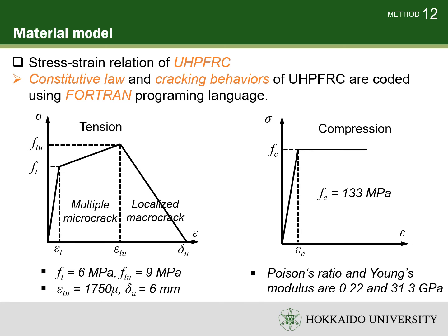Material model of UHPFRC. The stress-strain relation of UHPFRC in both compression and tension are shown in the figure. Constitutive law and cracking behavior of UHPFRC are coded using Fortran language. Under tensile loading, the typical behavior of UHPFRC is exhibited by three domains: elastic, strain hardening, and strain softening. The cracking stress and tensile strength are chosen as 6 MPa and 9 MPa respectively.